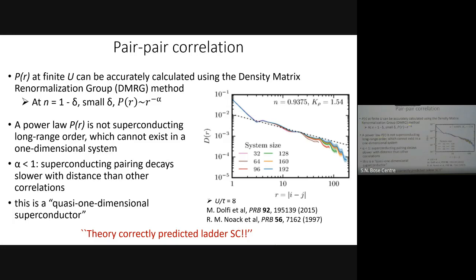We want to see how P(R) goes as a function of R. Does it actually stay finite at infinite distance? But this is quasi one-dimensional. This is a theorem. You can't have true long-range order here. It has to only decay slower than R to the minus alpha, with alpha less than 1. It has to decay slower than R to the minus 1. So people did calculations, and k is 1 over alpha. So alpha has to be less than 1, k has to be larger than 1, which is what people found.